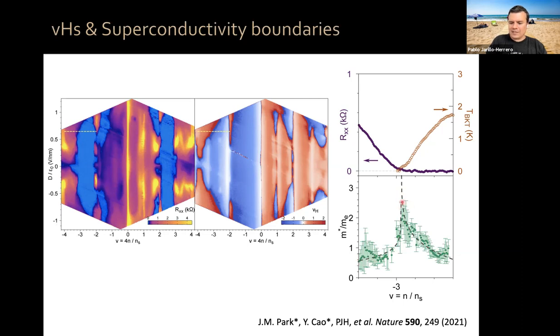The position of this maximum coincides with the Van Hove singularity here, okay? Which is something that you expect, you know, close to Van Hove singularity, your effective mass diverges, okay? And in fact, what you can see is that the Van Hove singularity, which coincides with the maximum of your effective mass, actually corresponds to the boundary of your superconducting phase.